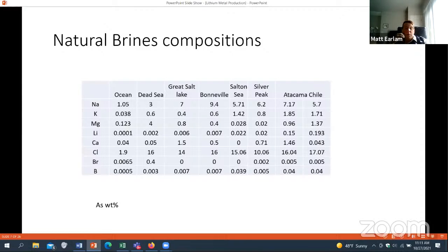And so all these brine processes really boil down to water management. I've got a lot of water to separate from the lithium. The less water I have to separate from the lithium, the more economical my process will be. Also notice there's some boron in these. Boron is a known killer of current efficiencies in electrowinning cells, molten salt ones. So we really have to get rid of this boron if we're going to do something electrolytically.